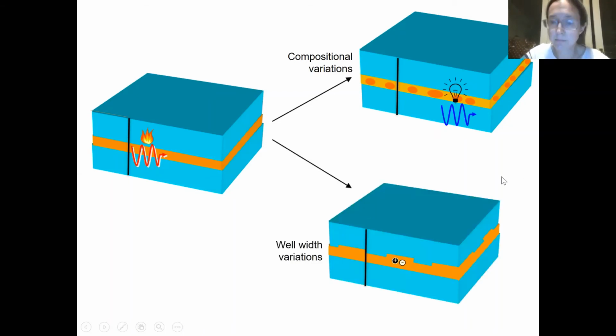It's also possible that changes in the thickness of the quantum well could have a similar effect. Now, the reasons for this are to do with exactly what kind of energy levels are available in a really thin structure like a quantum well. You remember I said it was only like 10 atomic layers thick. And it turns out that when you're down at really, really, really thin layers, their thickness affects the energy levels that the electron and hole are able to take, as well as the composition.